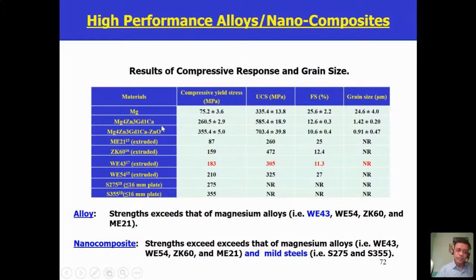Now you see the magic of nano reinforcement. You put zinc oxide to the level of maybe 1%, and you get another 100 megapascal improvement in the compressive yield stress. You get almost 100 plus megapascal improvement in UCS, and your failure strain is not compromised too much. It is compromised, but it is still beyond 10%. So anything beyond 10%, you can fabricate your material into intricate shape very well.